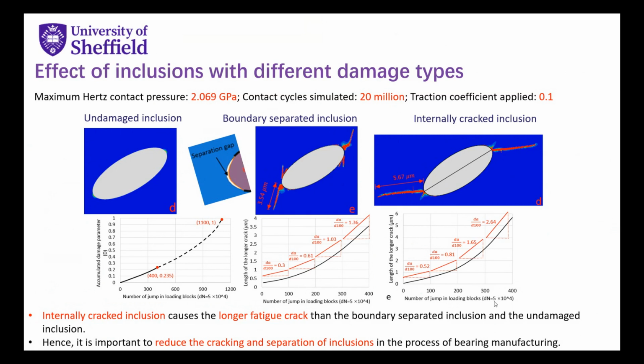In these three FE models, the maximum Hertz contact pressure is fixed, and the contact cycle simulated is 20 million, which is also fixed, and the traction coefficient applied is 0.1. The traction pressure is caused by the friction between the roller and the raceway, so this value is linked with the lubricating condition. When the lubricating is good, the coefficient is small. In this case, in all these three models, the value is fixed as 0.1 here.